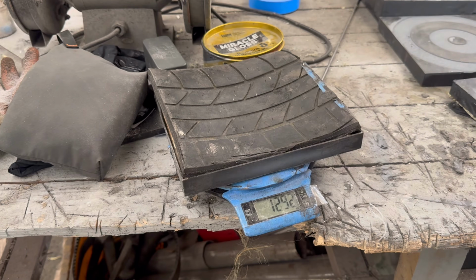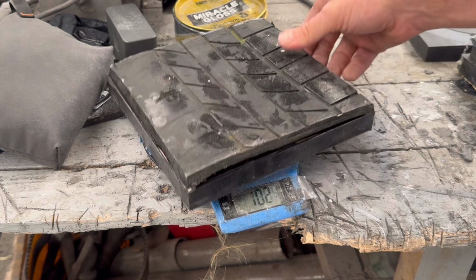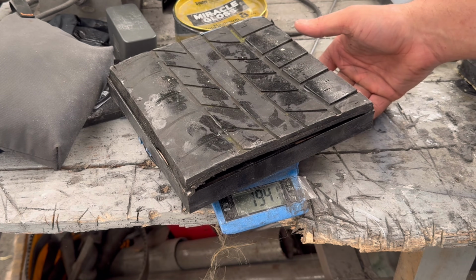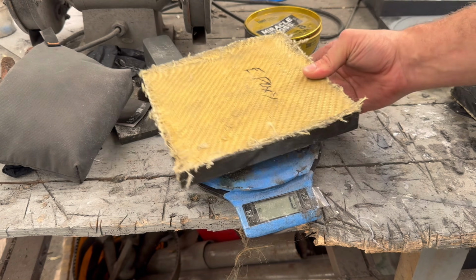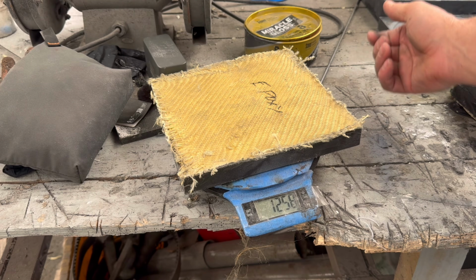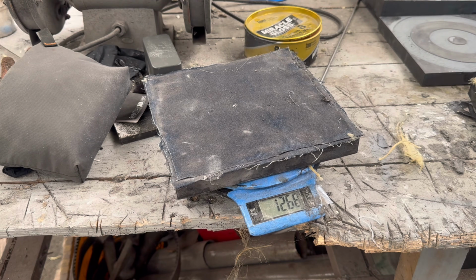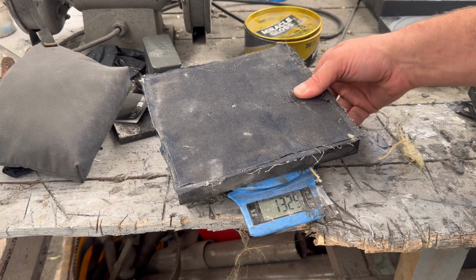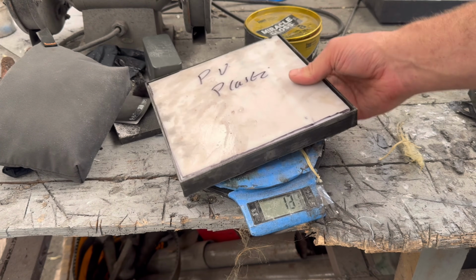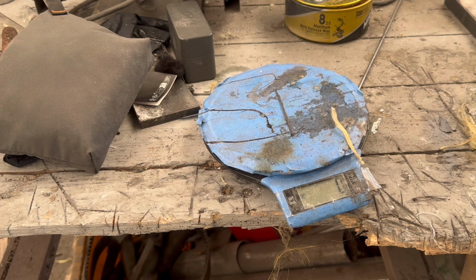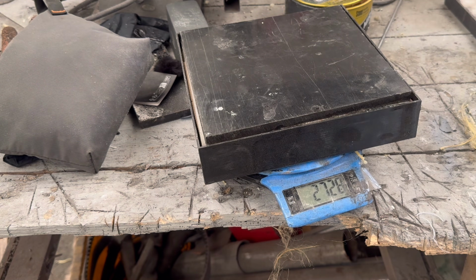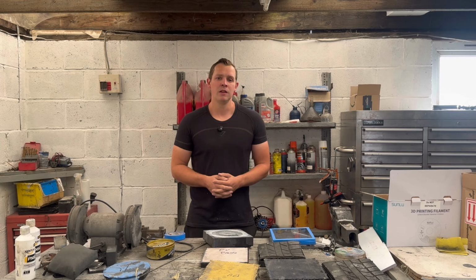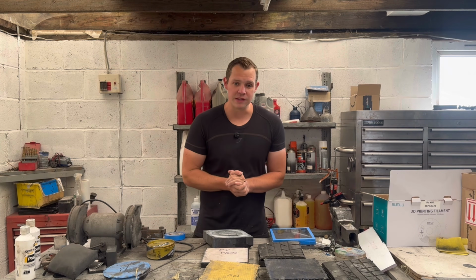And after finishing that filming, I thought I'd better weigh all of these off as a comparison. So the tyre with 1 layer of ceramic is 1200 grams. The tyre with 2 layers of ceramic is just shy of 2 kilos. Both of the Kevlar plates are around 1250 with no real difference between the resins. And the denim plate actually weighs about the same as well, which is unsurprising with how thin the backing plate is. With the plastic backed one also weighing around 1250. And then with the big 4 layer one weighing 2.7 kilos. So let's get testing and we'll review these afterwards.